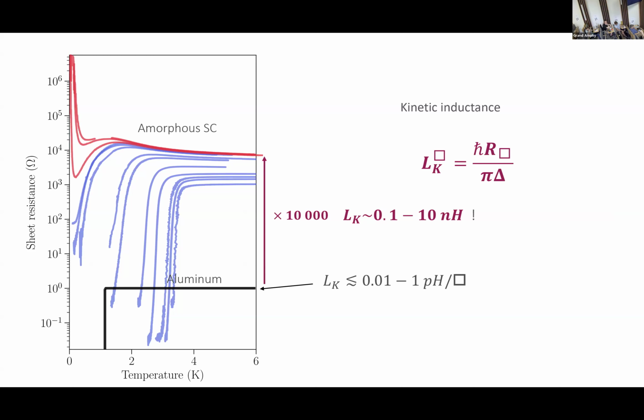Higher values, it's more like, of course, if you're an experimentalist, you might be interested in some design guidelines, and this formula works to within an order of magnitude. You can easily get something 10 times larger or 10 times smaller, depending on how you take the square, what delta you take, because we know from Benjamin's work that delta is not itself a well-defined quantity in strong disorder. But it will be hard to miss by, let's say, 3 orders of magnitude. So the idea is that it just gives you a motivation for why to go to high disorders in the first place.